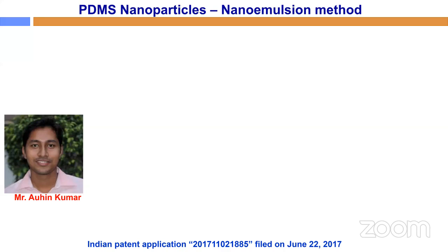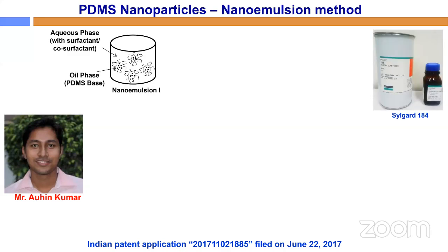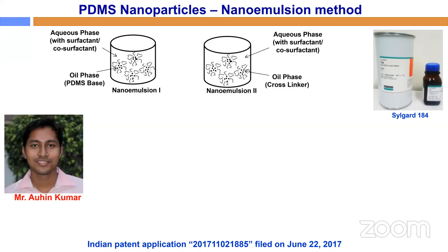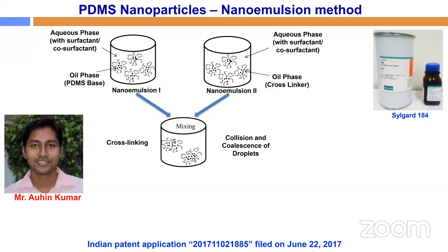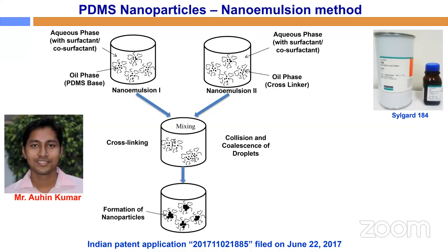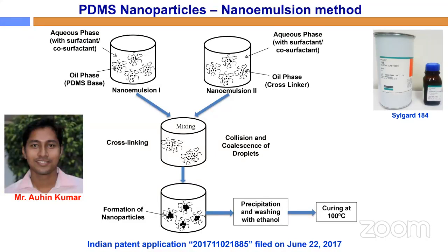So he came up with another method called the nano emulsion method. You prepare two nano emulsions. One nano emulsion has the PDMS base, and the other has the cross linker. We mix them together, cross linking happens, and then the nanoparticles form. But when he did the precipitation and washing with ethanol, no nanoparticles formed. All of them formed as a film. Again, we were very worried about why this was not working, because the confinement is happening and everything, so why is it not happening?